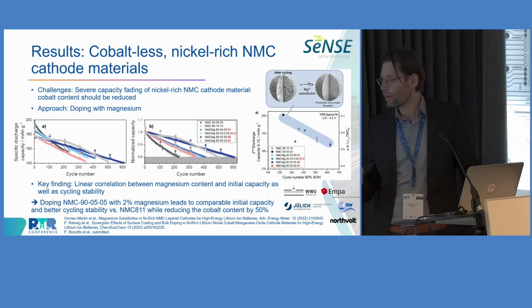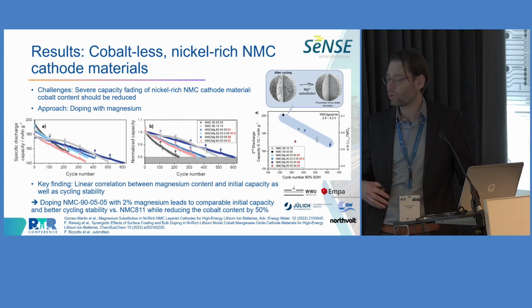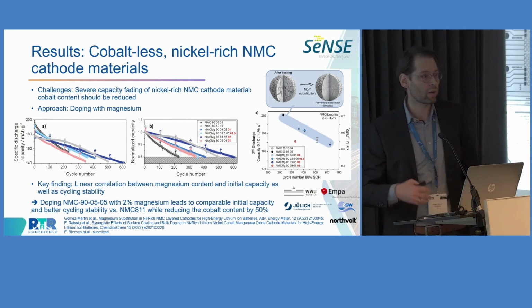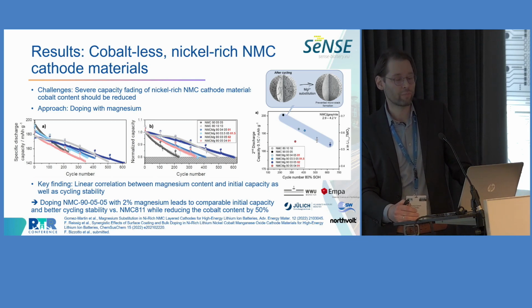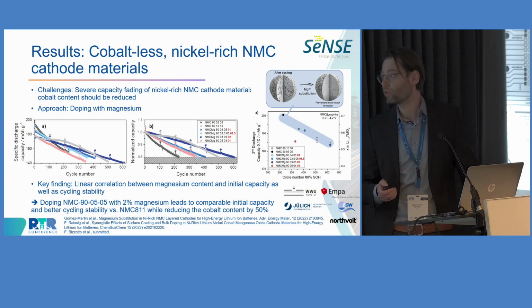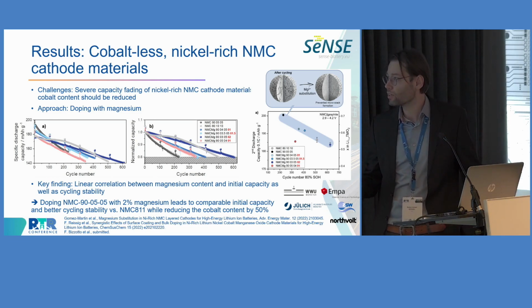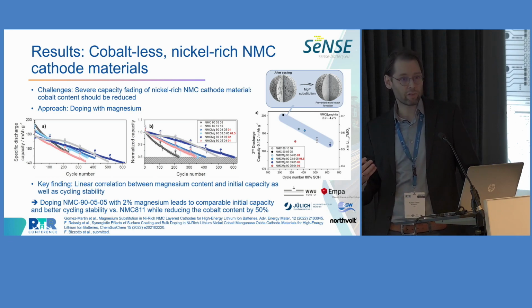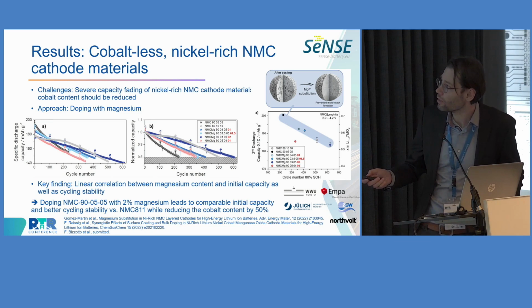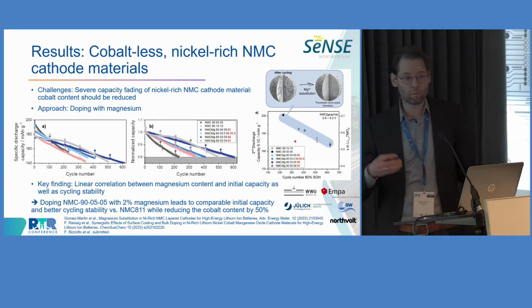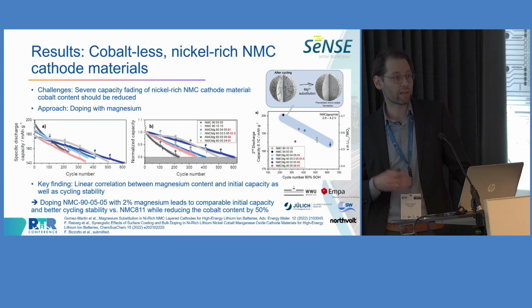So what we did here, and all these materials with these different compositions were synthesized with the same reactor. They all have similar properties in terms of particle size, in terms of morphology, in terms of surface area, which is important to be able to really compare the properties of these materials. And here in this example, we went for NMC 955, so we reduced the cobalt content by 50%. And as you can see here, if we compare here in gray NMC 811 with NMC 955, this really comes at a quite significant penalty in terms of cycling stability.